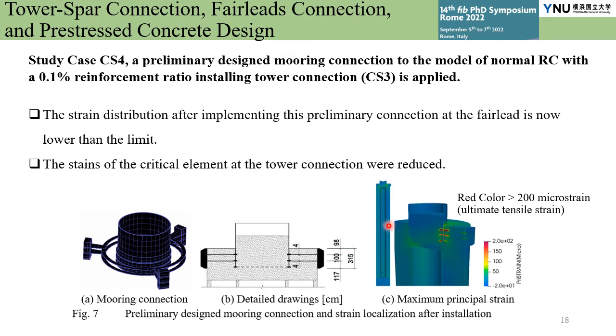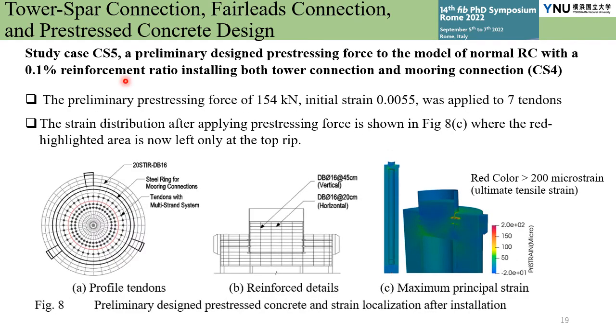The strain at the tower connection was reduced; however, it was still higher than the concrete ultimate tensile strain. Therefore, pre-stress design is necessary to strengthen this critical area. In study case 5, a preliminary design prestressing force is applied. In this case, the surrounding area of the rib plate is the area to arrange pre-stressed tendons. The preliminary prestressing force was applied to 7 tendons.